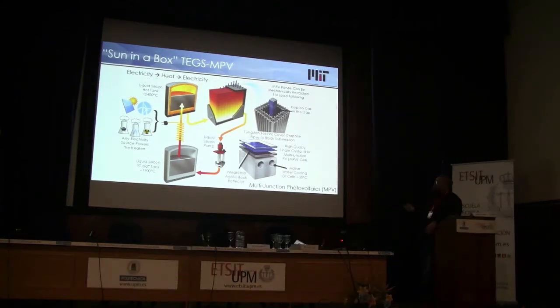And the reason that these PV cells are not normal is because, number one, they've got reflectors on the back, so they've got mirrors, so this is key towards recycling and keeping the light that you cannot convert efficiently trapped inside the system, so it would bounce off this mirror, go back to the piping, and keep the hot side hot so you don't waste the energy. And the second thing is we're looking at using multi-junction photovoltaics, so we call them MPV cells. I'll show you later. You can see the spectrum. For the cost that you expend to grow one junction, it's not a great increase in cost to grow a second junction and actually improve the efficiency significantly.